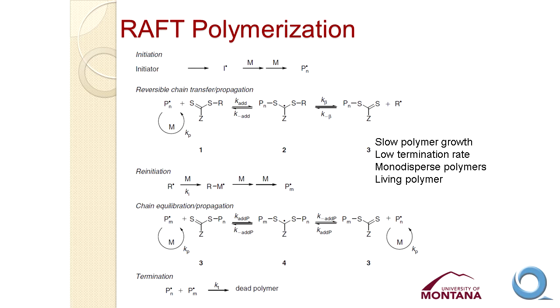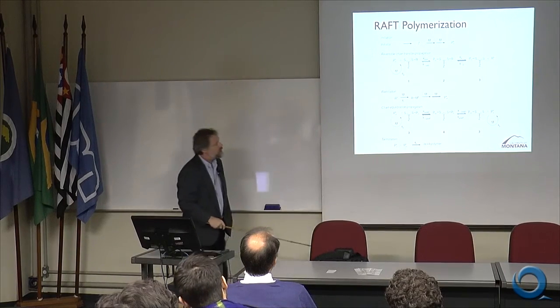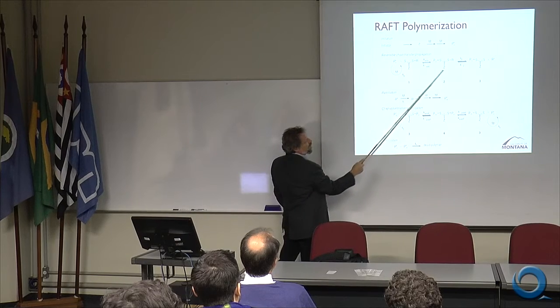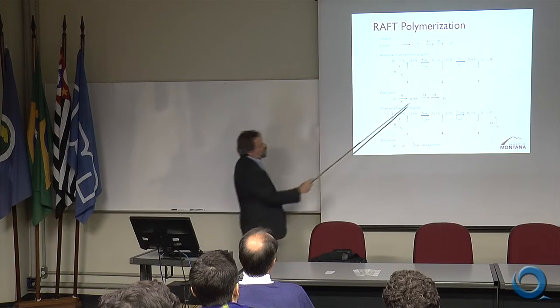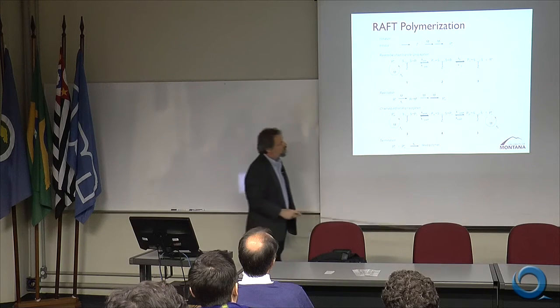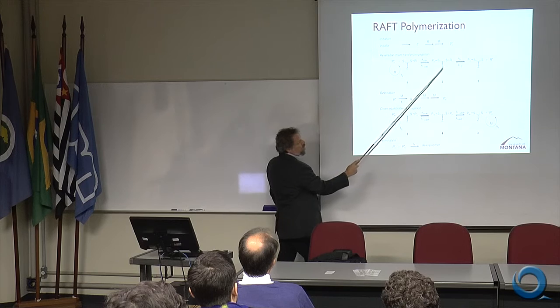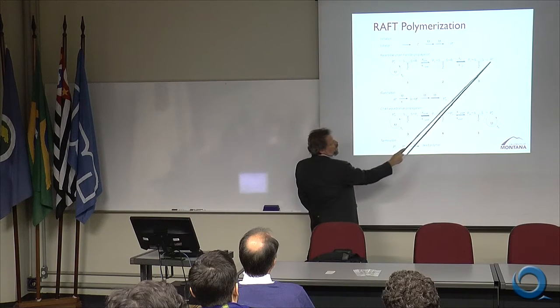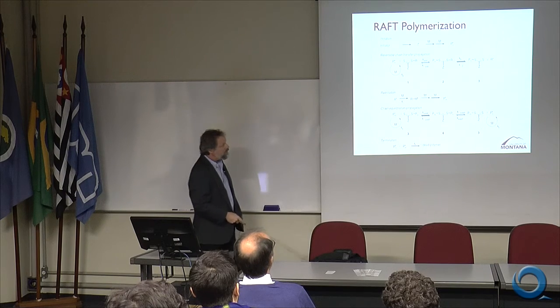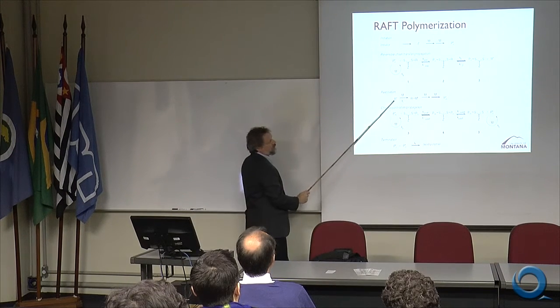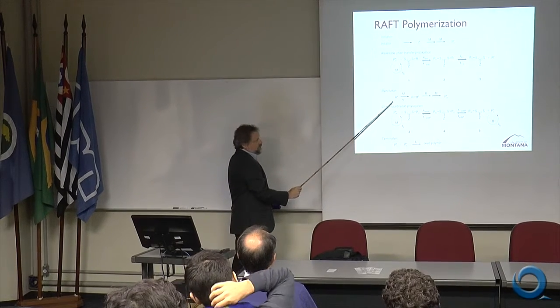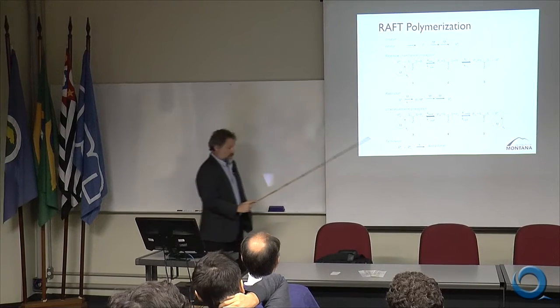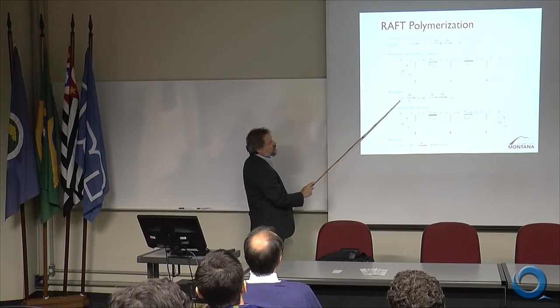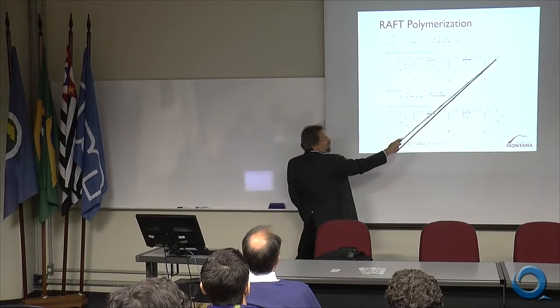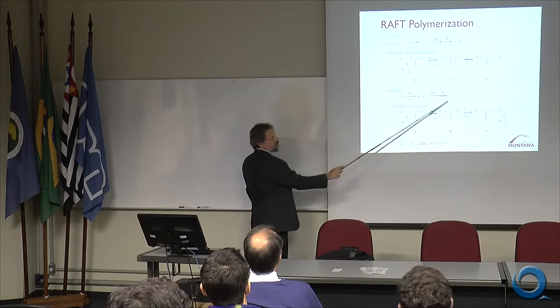Once we initiate the polymerization, we start to get a growing polymer chain like this. And that growing polymer chain will react with the chain transfer agent. It forms this intermediate, numbered 2 here, which is a fairly stable structure, stabilized by this Z group. The R group is a good leaving group, and so the R group will leave as a free radical. And that free radical can initiate additional polymerization. So essentially most of the polymerization is initiated by this process, where we're using this free radical that came from the chain transfer agent to initiate the polymerization.